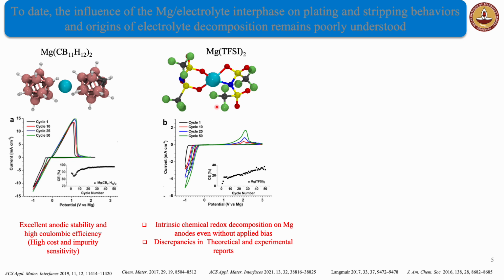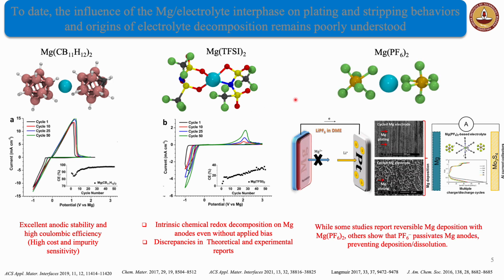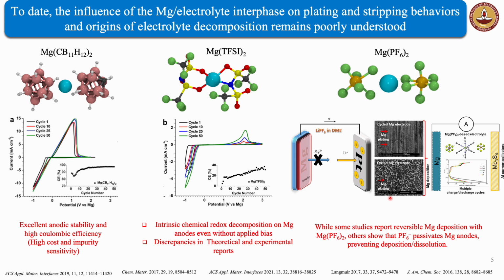Mg(TFSI)2 is one of the most promising simple ether-soluble magnesium salts, which is easy to prepare and commercially available. However, experimental studies suggest that it decomposes on magnesium metal anodes even without applying any bias, while computational studies predict that it should be stable under similar conditions. There are conflicting reports about reversible deposition with Mg(PF6)2 salt as well. While some studies report reversible Mg deposition with Mg(PF6)2, others show that PF6 passivates magnesium anodes, preventing deposition and dissolution of magnesium. So despite the progress with different magnesium-based electrolytes, the influence of the magnesium anode-electrolyte interface on plating and stripping behaviors and the origin of electrolyte decomposition remain poorly understood.